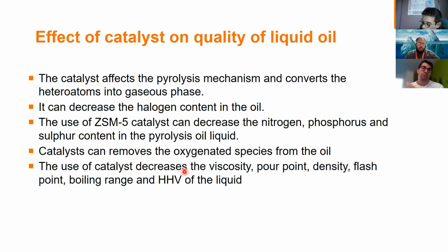For instance, a zeolite catalyst can decrease these types of heteroatoms like nitrogen, and it can also decrease phosphorus and sulfur content in the pyrolysis oil. Catalyst can remove oxygenated species from the oil. So for instance, if you have PET in the feedstock, it can induce oxygenated species in the pyrolysis oil. So these types of catalysts can also reduce these oxygenated species. The use of the catalyst can increase the quality of the oil by decreasing the viscosity, pour point, density of the oil, and different properties.